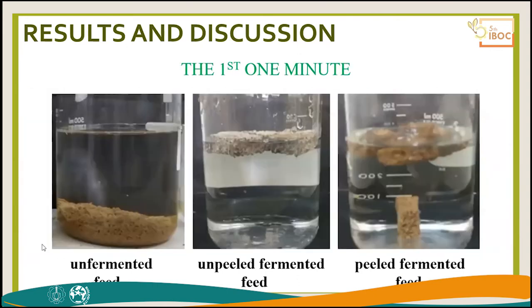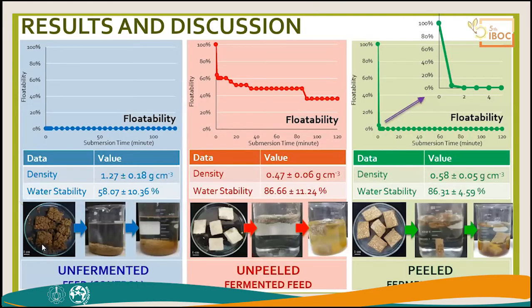And then we did the first test, using water. As you can see here, in the first minute of the test, the unfermented one completely sank at the bottom and disintegrated, so it broke down easily. But the unpeeled fermented feed and peeled fermented feed didn't disintegrate. The one without surface mycelium sank, whereas the one with intact surface mycelium floated better than the others.